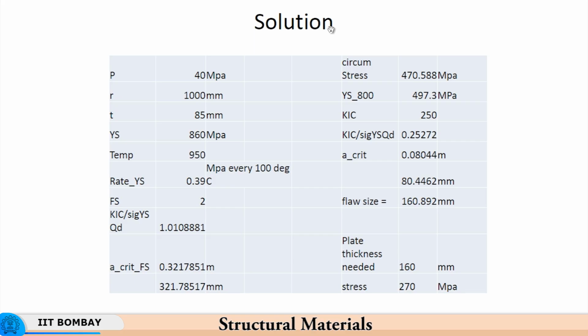So, it is about 470 MPa or so. The yield strength is 800. Now, this has been calculated not taking the thickness into account. I think this has been taken based purely on the internal radius, I guess, and so we get 470 MPa as the stress.